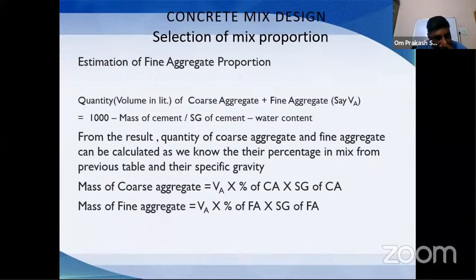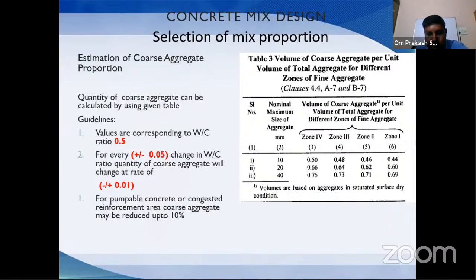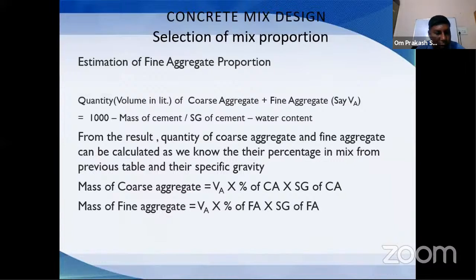Okay. If we have the volume of aggregate, here we have the proportion of aggregate, that is 62:38 or 64:36. Let's say 700 liter is the volume of aggregate, 700 liter, not kg, in the concrete. Of that 700 liter, let's say 40% is the part of fine aggregate, sand, and the remaining 60% is the part of coarse aggregate. So we will multiply the total volume of aggregate with the percentage of coarse aggregate and the specific gravity of the coarse aggregate. Just like that, we will multiply the total volume with the percentage of fine aggregate and the specific gravity of the fine aggregate. After that, we'll get the weight of coarse aggregate and fine aggregate.